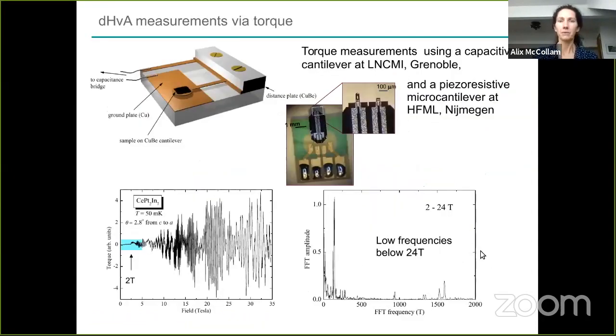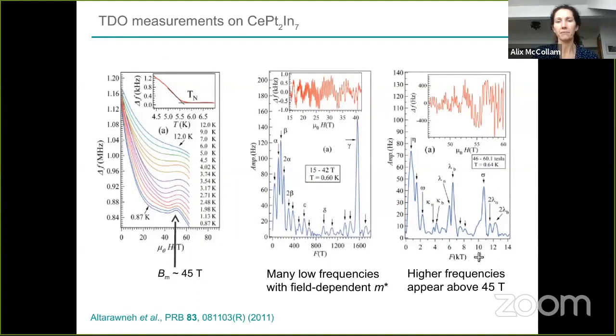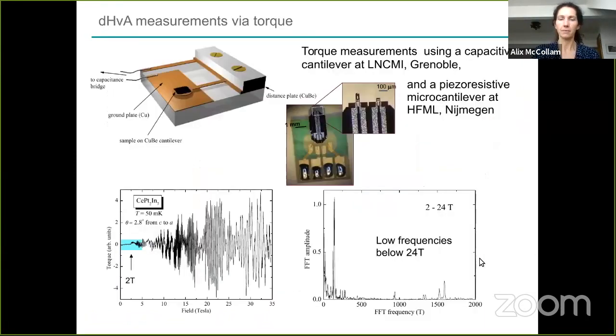So we did measurements too. This was one set of measurements, and there were still some questions about what happens at very high field and what's happening at lower field. So we were interested in looking some more at this material. We did not do tunnel diode measurements, but torque measurements. These were done in Grenoble and in Nijmegen and in Dresden. I will also show you some pulsed field measurements just before I stop.